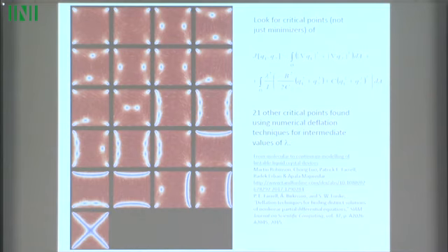You might be wondering what the blue bits and the red bits are. The red bits, informally speaking, are where the molecules are roughly well aligned, and the blue bits are where they are disordered, but disordered in the plane, which means mathematically they're actually negatively uniaxial. These are actually examples of negatively uniaxial interfaces in the 3rd dimension. But if you restrict yourself to a 2D analysis, these are what you would call defects. I think Miha was referring to these. He had blue regions near various corners on his fractal domains, and he was referring to these as defects. It's a similar scenario here, but obviously the geometry is simpler.